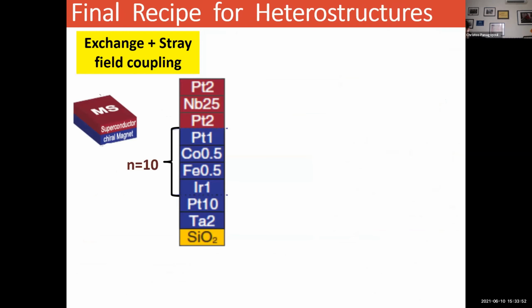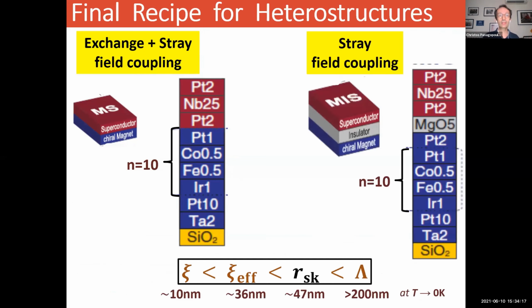You can see the first one has exchange plus stray field coupling. Why? Because in this heterostructure, we touch our superconductor, that is our niobium, directly on our chiral magnet, the material that I mentioned earlier, which is platinum, cobalt, iron, iridium, 10 repeats. The other material that we will have is one with stray field coupling, because we inserted an insulator, specifically magnesium oxide, between the superconductor and the chiral magnet. I will call the one which is superconductor chiral magnet MS for magnet superconductor, and the other one superconductor insulator chiral magnet MIS for magnet insulator superconductor.